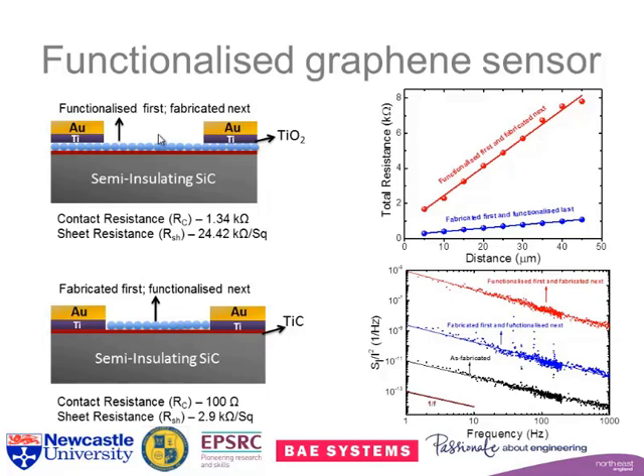Now, one of the big challenges in sensors is your noise floor. So our basic noise is right down here, and this is sort of like on the edge of beating everybody else's at the moment. But if we functionalize first, it goes up by 6 orders of magnitude. So one of the things we did was we built the sensor, and then we functionalized. Seems obvious, but the process development required to keep this surface perfectly clean so that we can functionalize whilst we go through all these horrible dirty processes like photolithography and metal deposition and etch is actually quite a challenge.